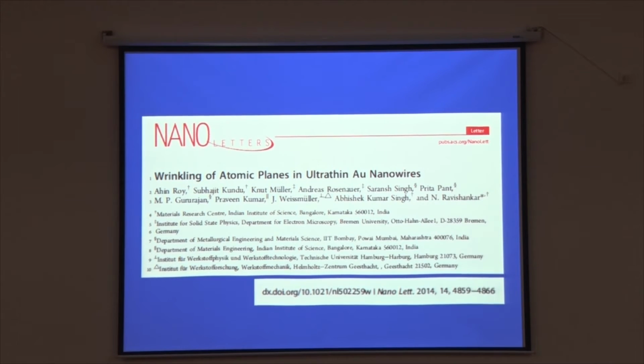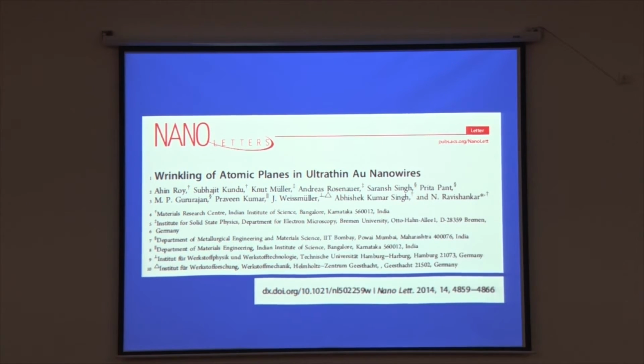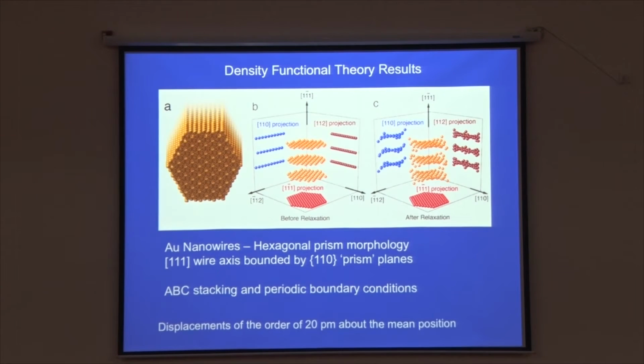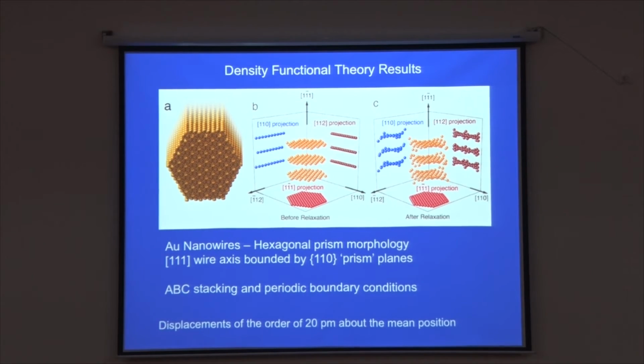Whereas when you have a wire, the planes that are normal to the wire direction now become saddle shaped. They undergo wrinkling because of this kind of relaxation. To put it in a form, this is the starting state where we have ABC stacking of the gold in the gold nanowire, whereas after relaxation we see that atoms have significantly moved up and down the plane. To put it in a cartoon form, these basically form saddles. They have positive and negative curvature.